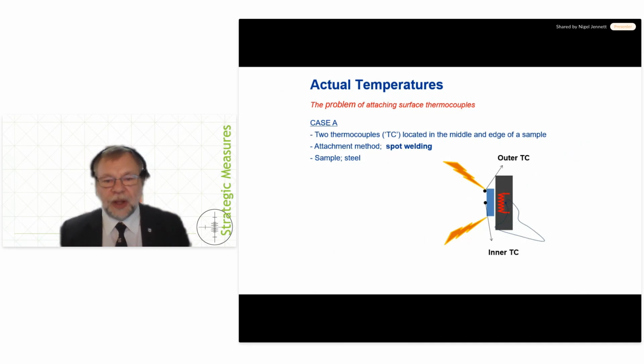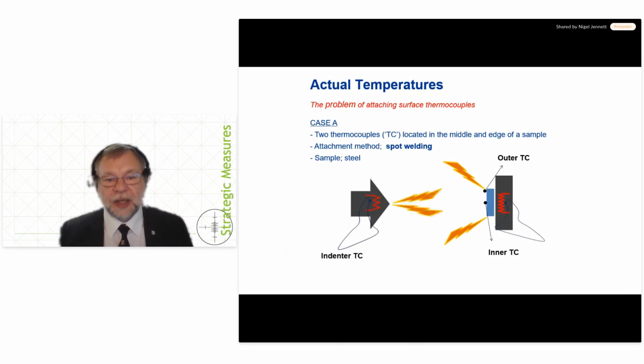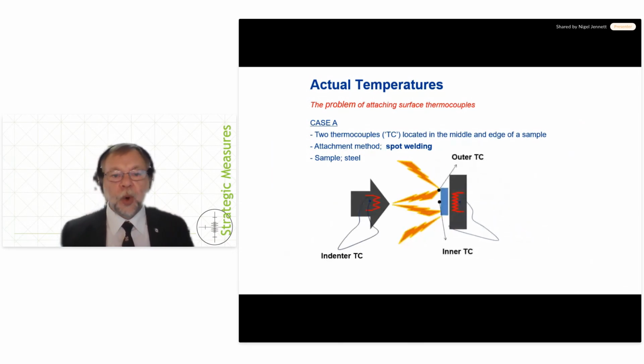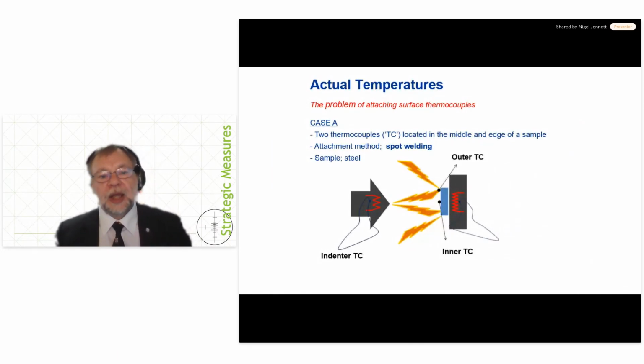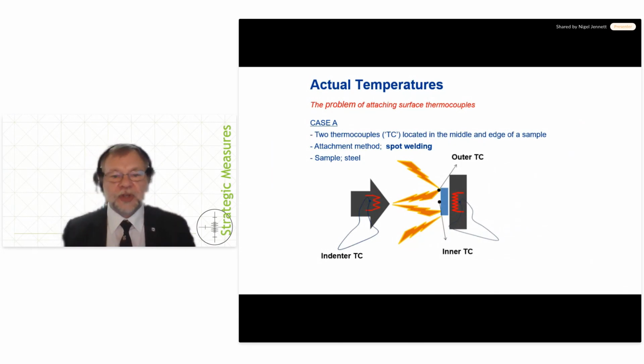So if you have a heater, a couple of thermocouples, you've got this radiative loss at the edge, which means the edge thermocouple is cooler than the center thermocouple. You've got your indenter, it's also emitting. And when you move one into the orbit of the other, then the input energy from the other heater increases the energy level that you have on the surface above what it was when it was far away. And so the temperature of the surface for the same powers in both of those heaters goes up, because the energy balance, which gives you the energy level, which gives you the temperature, has changed.